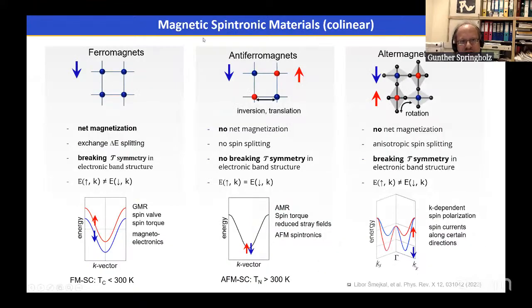Now, classical magnetic spintronic materials are usually ferromagnets, as shown here on the left-hand side, where basically the spins or the magnetic moments are aligned in one and the same direction. So we have a net magnetization of the system, and this magnetization, this effective magnetic field, acts on the electrons, produces an exchange splitting of the spin up and spin down electrons, as shown here on the lower left side. So this breaks time inversion symmetry and induces a splitting of the electronic band structure in majority and minority carriers with spin up or spin down spin polarization. This effect is usually used for GMR, spin valve, spin torque devices in magnetoelectronic systems, for instance, data storage with hard disk drives, etc.